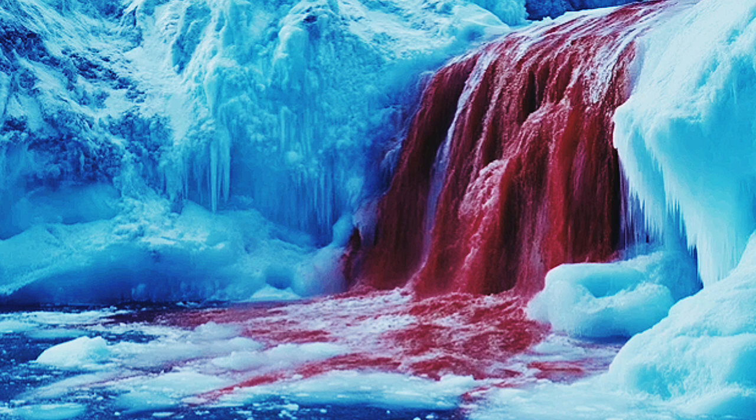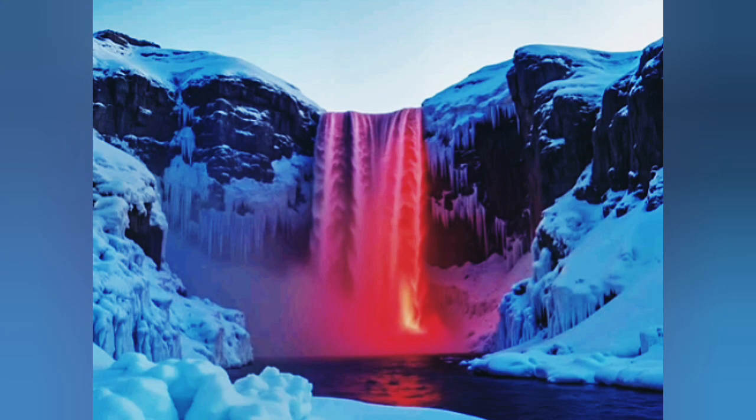Wow. So it's not just iron oxide, it's this complex little amorphous ball of stuff. How do they actually form and make the water red? Good question. The thinking is you start with this brine beneath the glacier. It's trapped, very salty, and loaded with dissolved iron in a specific chemical state, Fe2+. Okay, the ferrous state. Right. Then when this brine manages to seep out at Blood Falls and hits the air, bam, oxygen. Oxidation happens instantly. The Fe2+ iron loses an electron, becomes Fe3+ or ferric iron, and this process triggers the formation of these tiny disordered nanospheres containing iron, oxygen, hydrogen, essentially iron oxyhydroxide.